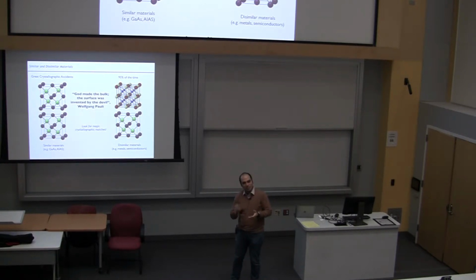So then the game becomes to be smart and see, okay, maybe the lattices don't match, but maybe twice that lattice matches one lattice size of the other one. Or if I grow it in a 1-1-1, now I can find some domain matching and all that, right? So those are very helpful, actually. We can be guided by some simple theoretical models or MATLAB programming even, just asking for the lattice parameters. So we do a lot of that.